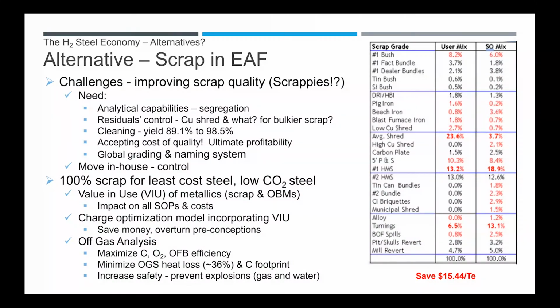If we are going to use scrap in the EAF, we need to, apart from improving the quality of the scrap, as I've said, look at programs or models that will allow assessment of value in use and charge optimizations, incorporating that, and use off-gas analysis to maximize the chemical energy inputs, minimize off-gas system heat losses, which can be as high as 36% of the input energy, and increase the safety, of course, by reducing explosions. And there's an example on the right, which I'd love to go through, but I don't think there's enough time. But if you optimize your scrap, you can, in this particular instance, save $15 per ton. Next, please.